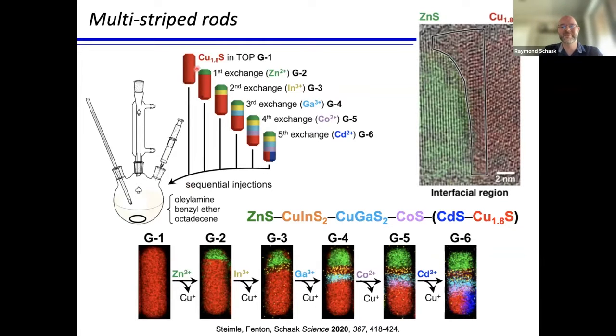What's the molar ratio of zinc 2+ to the copper+ cations that are present in the nanorods? And in doing that, we can basically carry out multiple sequential cation exchange reactions where the amount exchanged is defined by those molar ratios. The order in which the materials integrate into the nanorod is simply a matter of what order you injected the metal salt solutions.